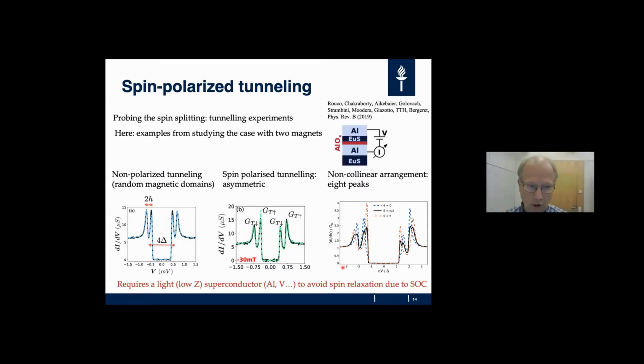Okay, here is an example of a recent experiment. This is not the first experiment to study spin splitting, but it's just a representative one. So how you see the spin splitting in a tunneling experiment is just you have the spin split gap, which is basically the distance between these two peaks, twice the induced exchange field.